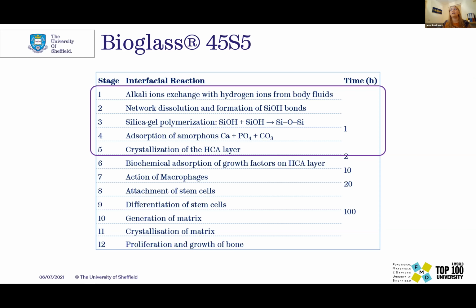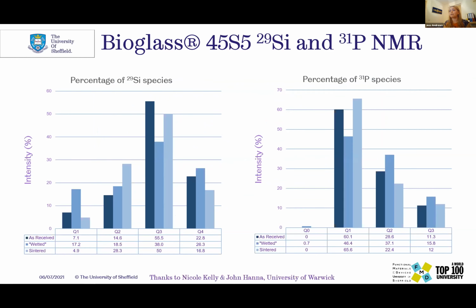So we did some NMR with the help of Warwick University to look at how the structure of the glass changed: as received material, once we'd wetted it and ground it up before putting it into the press, and once it had been sintered completely. You can see a dip in the higher Q3 silicon species, so you're getting a reduction in the overall network connectivity, which is what you would expect. And then when it's heated and resintered, you get a repolymerization in the silica.